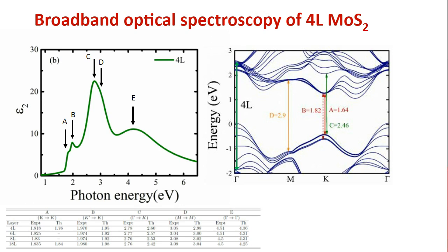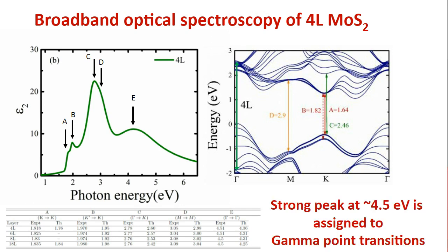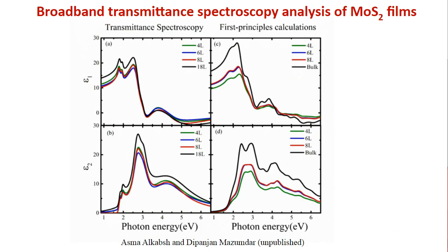So again, long story short, we assign this E transition, interband transition, to direct transitions at the gamma point of the band structure. So this is what's going into the paper, but it may be too technical. More or less, we have used the broadband properties that are offered by our spectrometer here. And here I'm showing the real and the imaginary part of the dielectric constant.